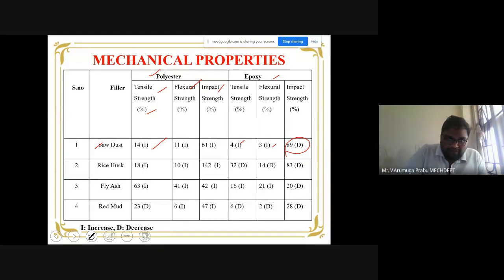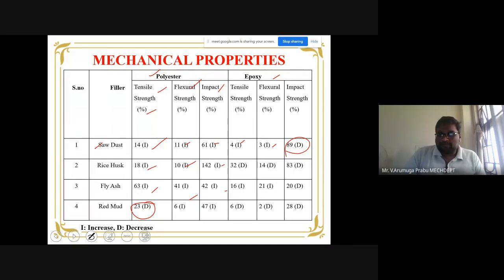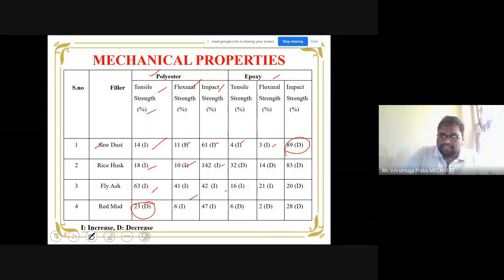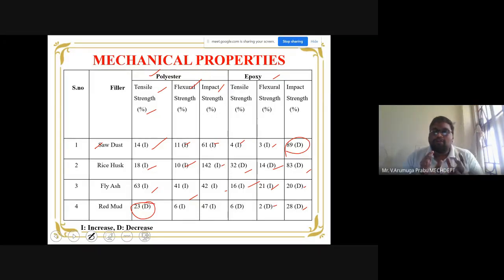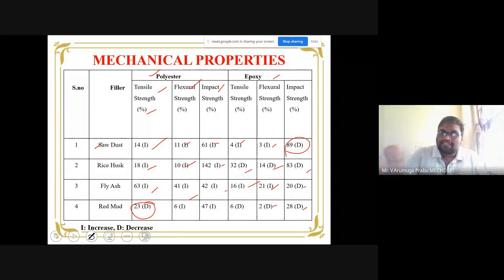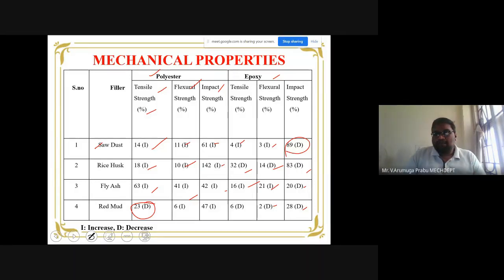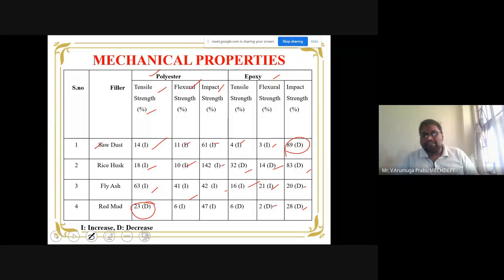If you see overall, collectively all the four wastes, you are able to notice only increases. In this particular case, only decrease. Probably they don't have enough capability to withstand the pulling force. On the other hand, in the epoxy also, in most cases there is an increase, but the decrease is on the high side. So this waste is not at all compatible with epoxy, because we are able to notice a drastic decrease in the mechanical properties, exclusively your tensile, flexural, and impact properties. So when compared to polyester, epoxy is not well compatible with the industrial waste fillers.